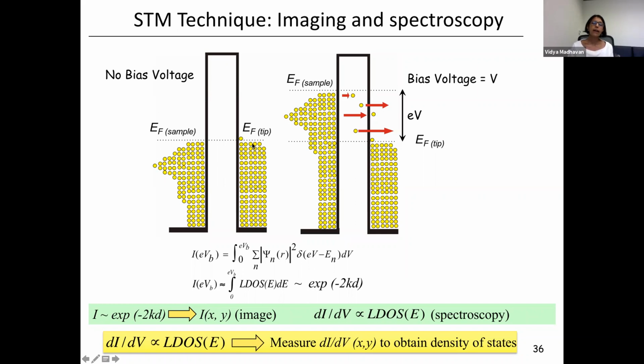And then when you turn on some potential difference between the two, just a bias voltage, you raise the Fermi energy of one with respect to the other. And now electrons can tunnel from the filled states of the sample, in this case, to the empty states of the tip. And it is this tunnel current that we measure. And this is the only measurement we make. We measure the magnitude of this tunnel current as a function of position as the tip is rastered across the sample. We measure it as a function of bias voltage. And we can even measure it as a function of distance from the sample. But the only actual measurement we make in an STM is the magnitude of the tunnel current.